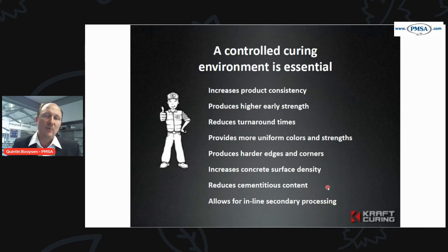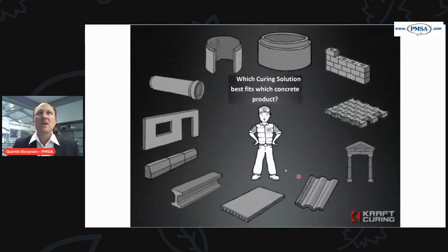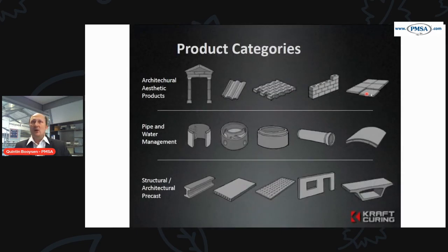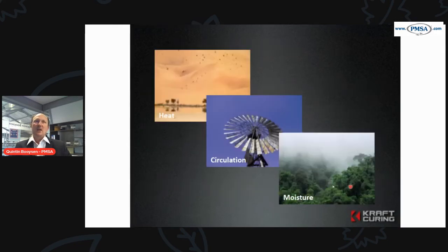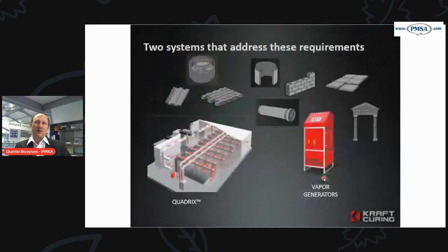So in the brick and block industry, you may want to grind the surface after 24 hours, hammer it, get a bush hammering effect. The stronger you can get your product and the quicker, the more secondary processes you can introduce later. There are different types of curing systems for different products. So paving will have a different system to beams, for example. Product categories: we look at architectural, we look at pipes and water management, and we look at structural elements. So we have a combination. We need to add heat or maximize the heat of hydration, capture it. We need circulation to get even, and we need that moisture to maintain the curing environment.